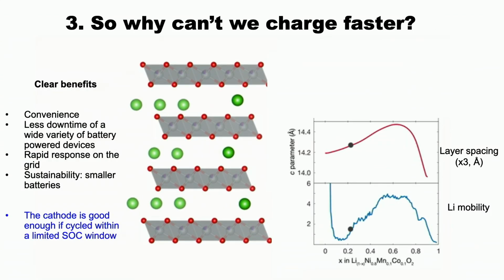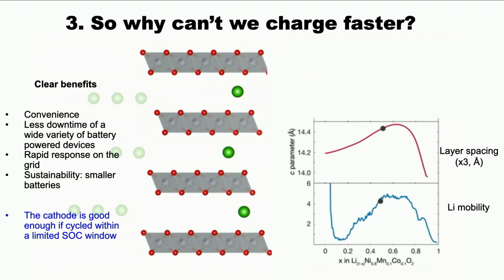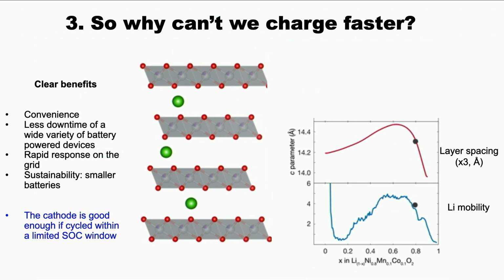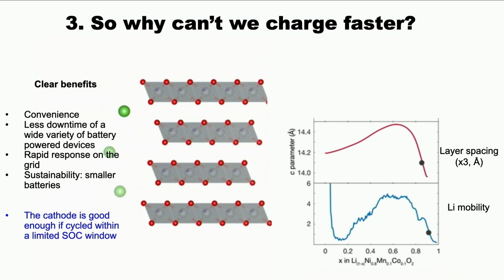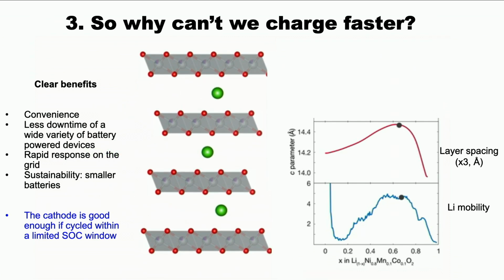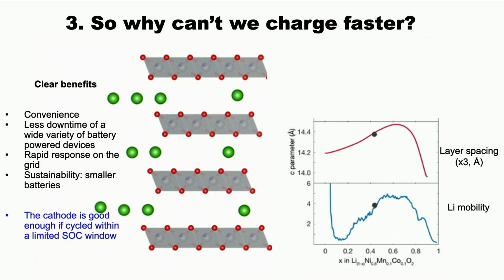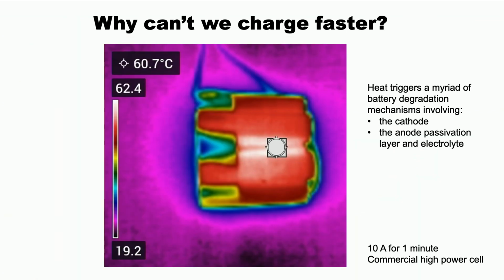So let's just think about why we can't charge faster. I've talked about the NMC materials and the LCO materials, and as long as you're working in the right regime, between about 20% and 70%, the lithium mobility is pretty good. So why can't we just charge our batteries infinitely fast? Well, this is a Samsung cell that we put 10 amps through for 1 minute, and this is not a recommended experiment. It heats up, and it goes to above 60 degrees very quickly. And 60 degrees is the temperature at which the SEI, the passivation layer, starts to fall apart. The cathode, when it's oxidized, is metastable, and things go horribly wrong.